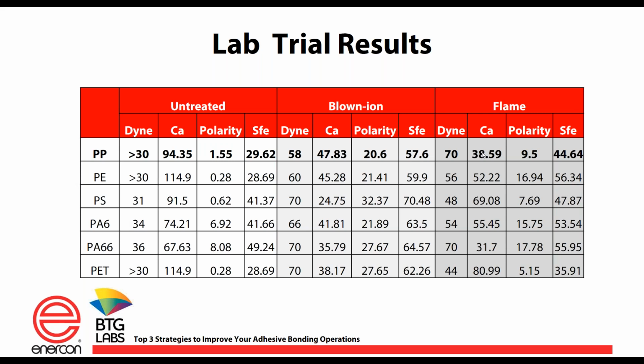You also have polyethylene. We're not going to go through this whole list. This is just so that you can have it when you download the webinar. You've got a much higher contact angle of 114, and you can get down into the 40s or 50s after a blown ion or a flame treatment. So one of the things you do see here is that different materials react better to different chemistries added to the surface. Again, plasma is going to put hydroxyl groups on the surface, and flame is going to put carboxyl groups on the surface. In some situations, that blown ion is going to work a little bit better. In some situations, the flame is going to work a little bit better.